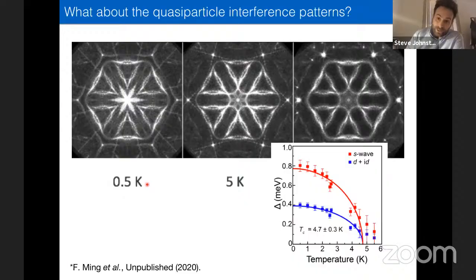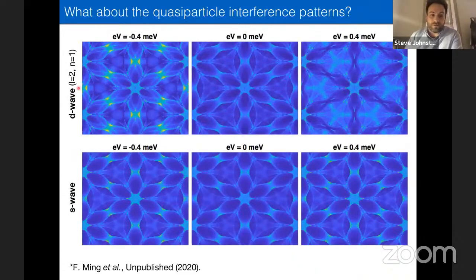So we then go simulate that to try to understand what's going on. I put in the d+id pairing symmetry that DCA tells us is the leading instability, and I just rerun the calculations and look at what the quasiparticle interference pattern does. Again, we get patterns that roughly look like what they look like in the normal state, but then I get the formation of this sort of petal-like feature showing up in here, along these directions. At zero bias voltage, they're suppressed, unlike the experiment, but at positive bias voltages, we see this flower-like pattern is still there in the theory images.